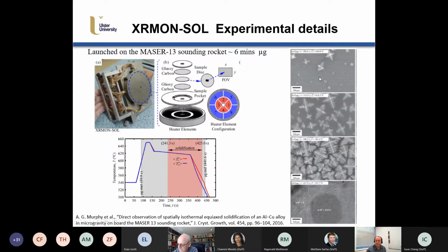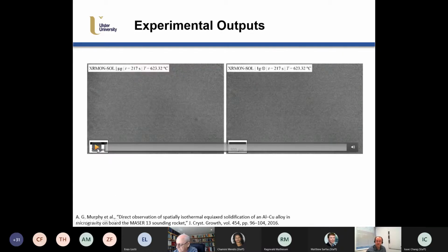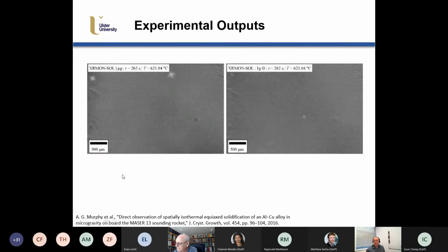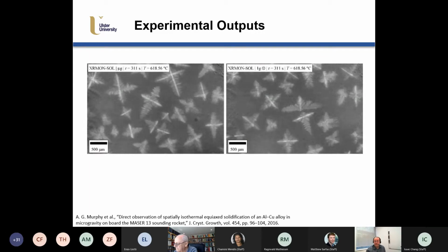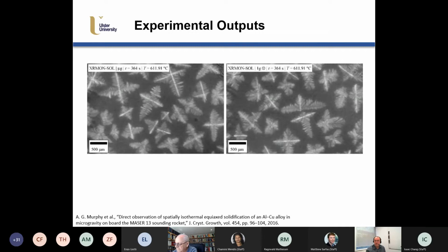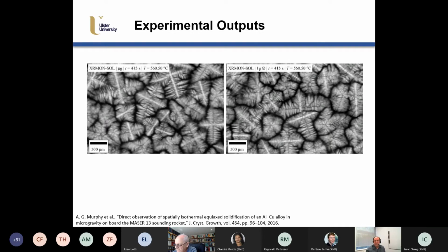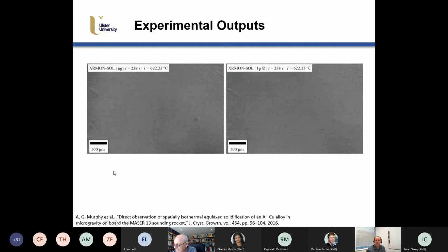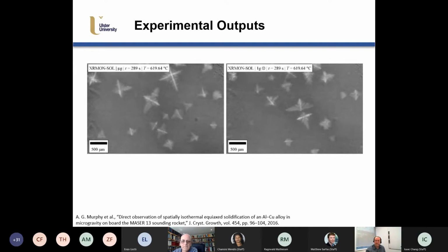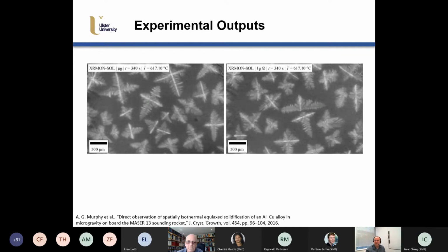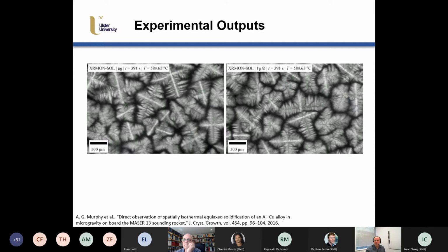I'm going to show you here, there was some equiaxed solidification observed. So hopefully you can see this. The left-hand side is the microgravity, and the right-hand side is a repeat experiment on ground. You can see the equiaxed solidification. And finally, if you look closely, you can see the eutectic transformation occurring as well at the very final stage. So you see that it's quite slow, then it goes through a rapid cooling phase, and then it goes eutectic like that. Okay.